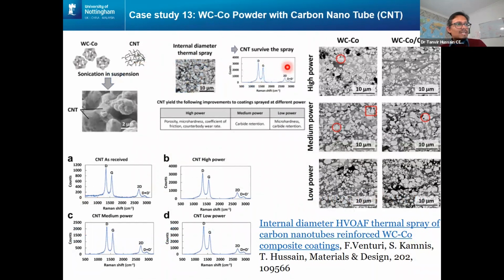This one is not suspension. We are working with an Innovate UK project where we're looking into carbon nanotubes. In industry, tungsten carbide cobalt powder is the most commonly used powder for coating deposition, and we were using carbon nanotubes and spraying them. Carbon is a great material, but it doesn't like high temperature. So quite a lot of work goes into modifying the feedstock in a way that you can get them into a coating in a usable format.